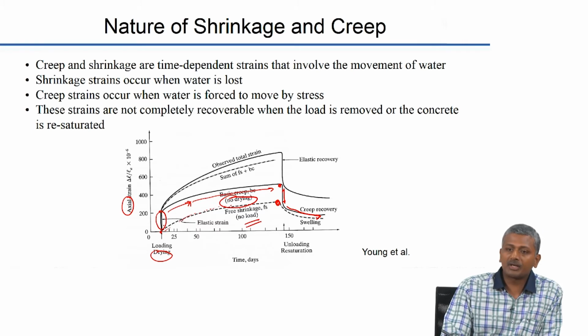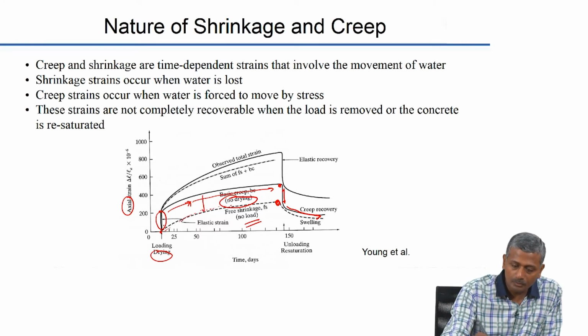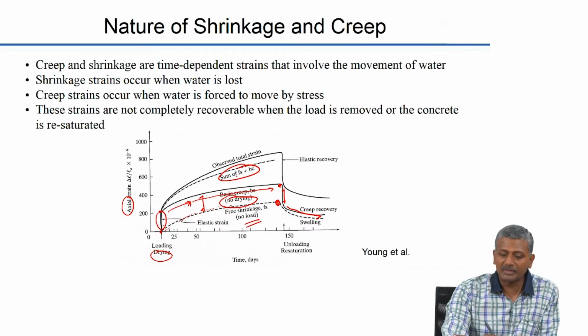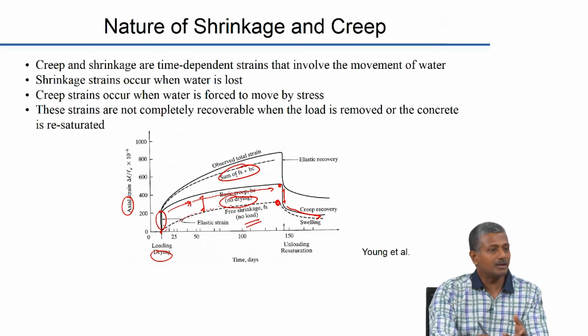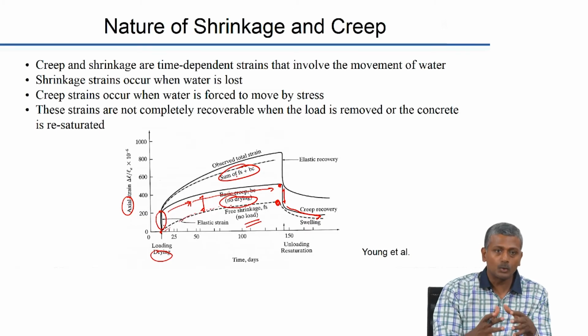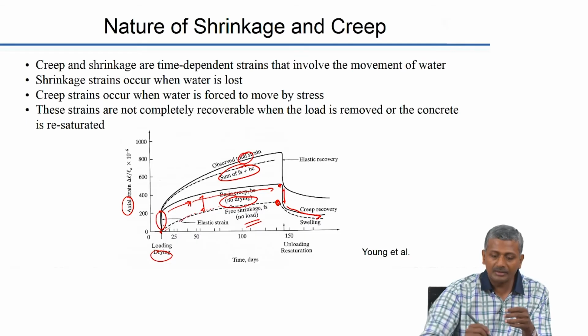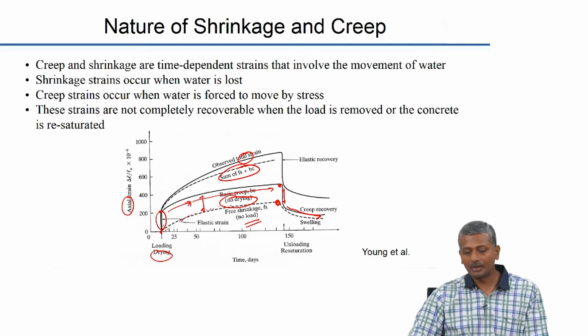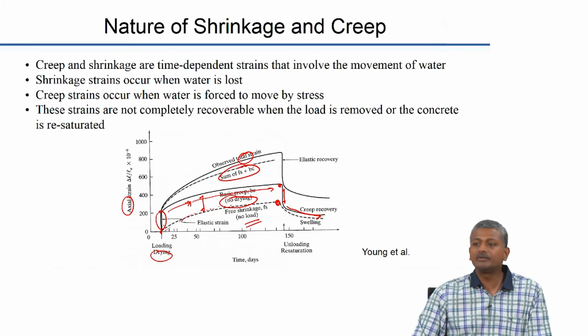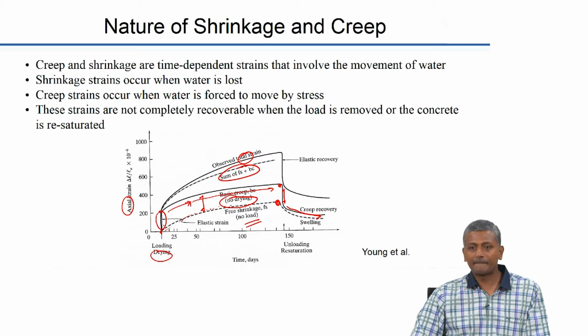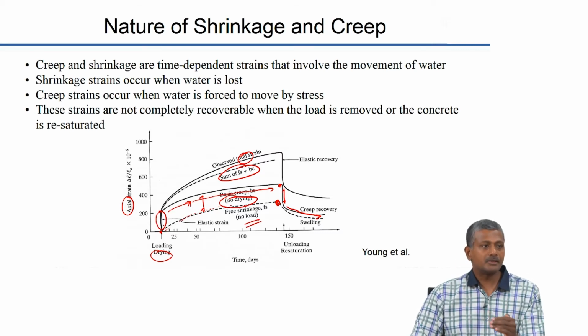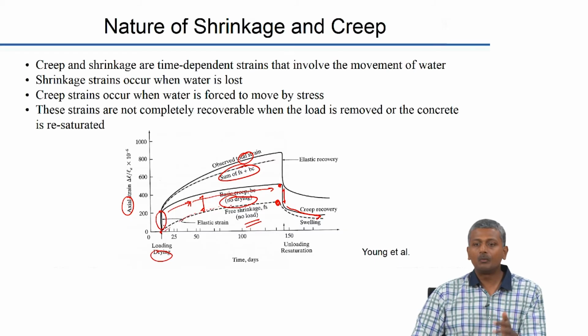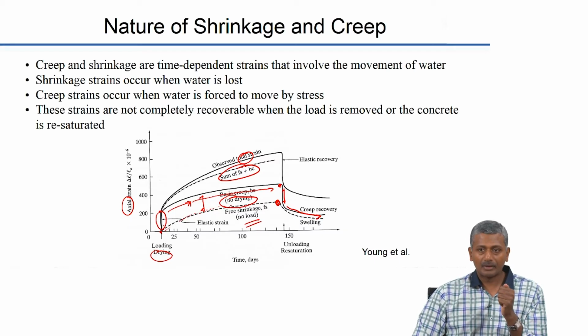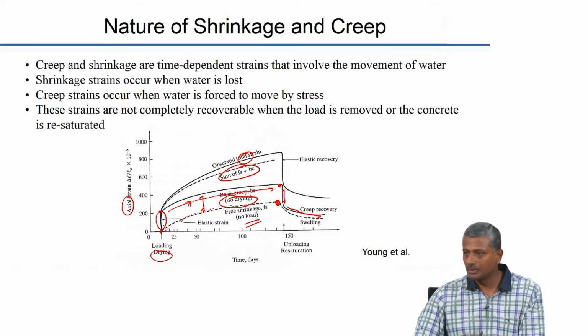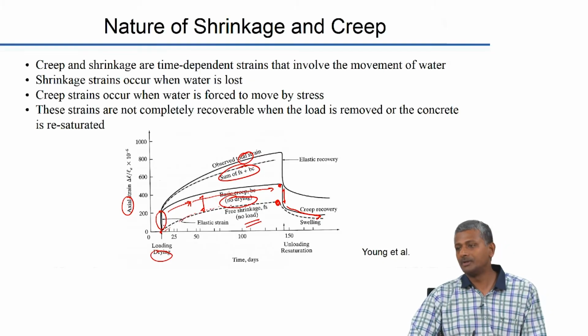In reality, creep and shrinkage are going to happen together. So, if you sum up the free shrinkage and the basic creep, you will get this dashed line, sum of basic creep and free shrinkage. But in reality, the actual deformation that you observe for materials that are undergoing both loading and drying is much higher than the sum total of your free shrinkage and basic creep. This suggests an additional mechanism which is governing your deformation. What is that? The sum total of free shrinkage and basic creep is lesser than the actual deformation that the material suffers when it is loaded and is drying at the same time. So, there should be some additional contribution which is leading for this curve to be higher than that of the sum of free shrinkage and basic creep.